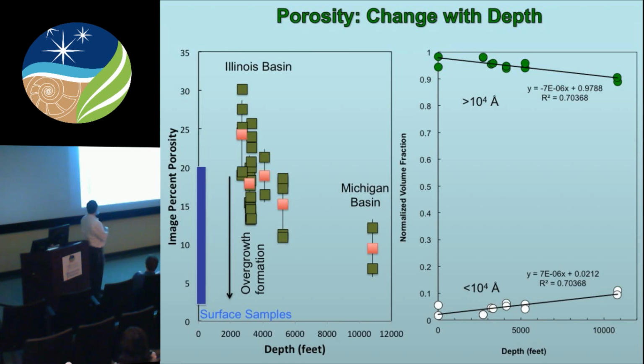Now, if we plot the porosity as a function of depth, this, on the left, shows the porosity simply from imaging. So this is SEM imaging. And essentially it shows what you'd expect. As you get deeper and deeper into the sample, the overall total porosity decreases as the material gets more and more compacted. That should be expected.